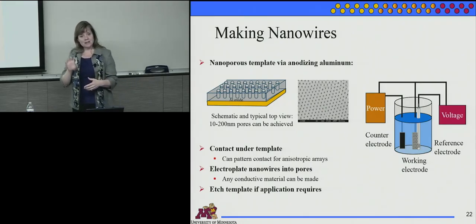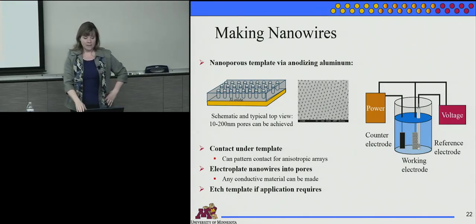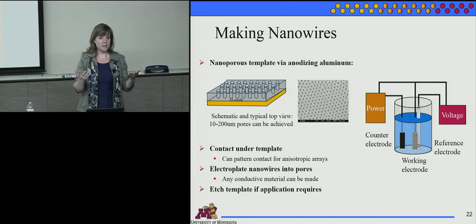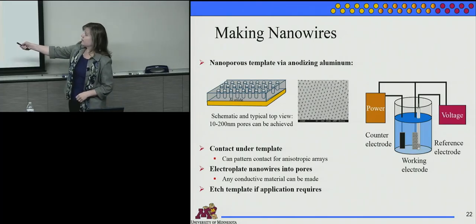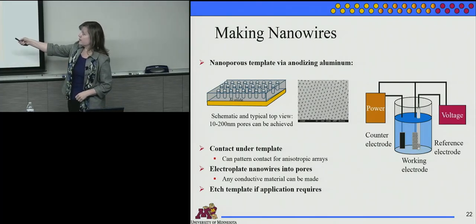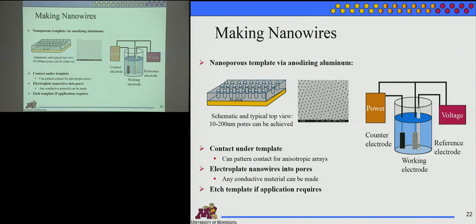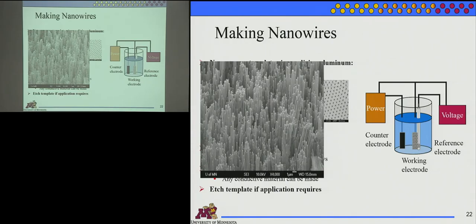And then you can dip into the electrolyte and not worry about having the backside coated, because that swamps the entire procedure. All right, then in this case we need a reference electrode, which is this kind of bubble thing here, because you really need to know exactly what the potential is at your surface, because you're relying on the reduction potential and how much below that you are when you're depositing. And we still need the counter electrode and so on. All right, so that's what they look like.